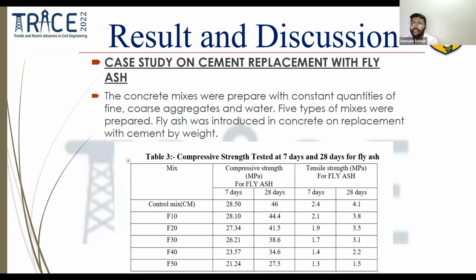Now, further case study on cement replacement with fly ash. The concrete mixtures were prepared with constant quantities of fine aggregate, coarse aggregate, and water. 5 types of mix were prepared. Fly ash was introduced in concrete as replacement for cement by weight. So here we prepare 5 other mixtures with fly ash: F10, F20, F30, F40, and F50.